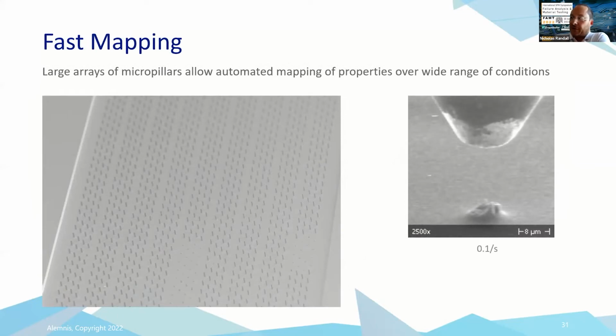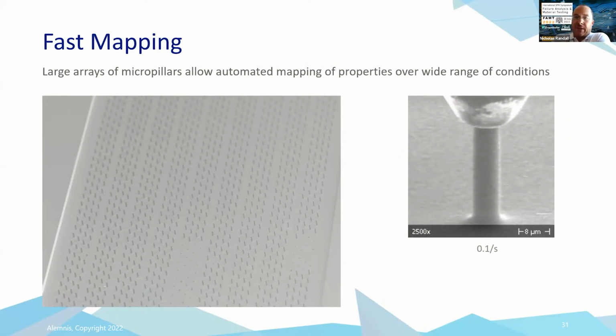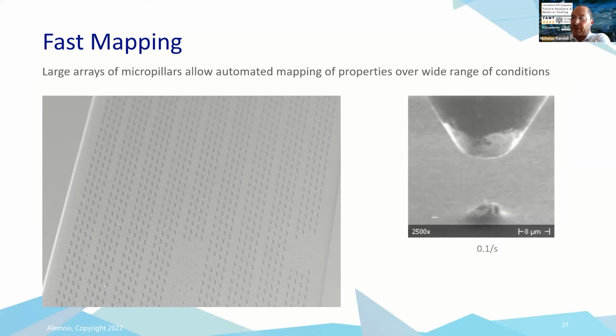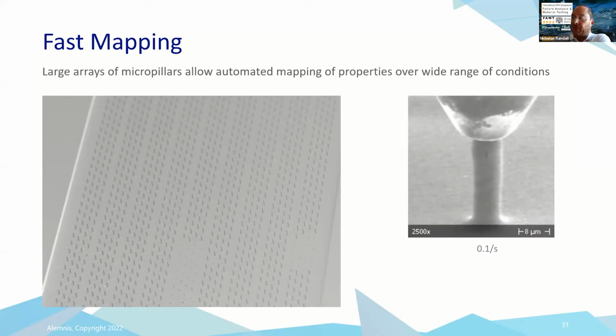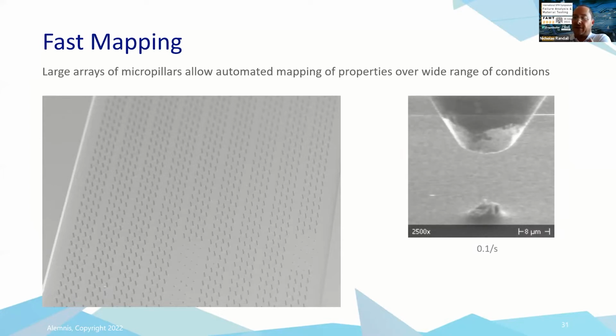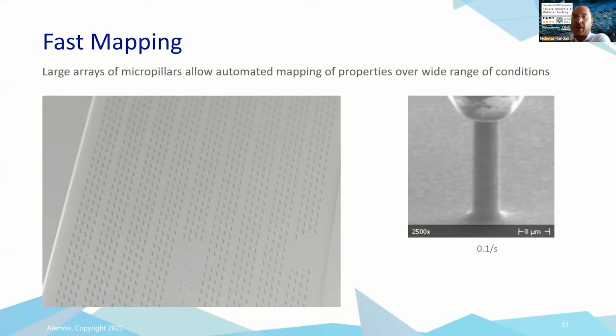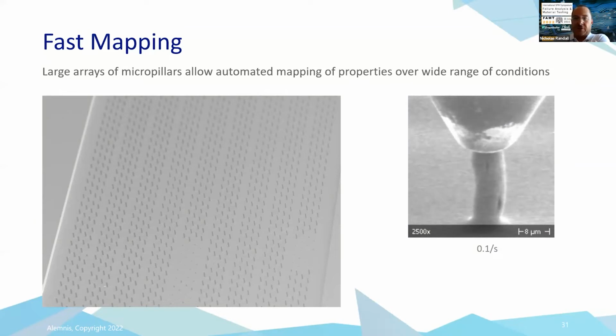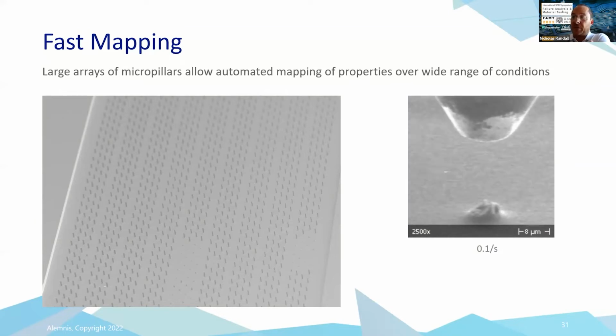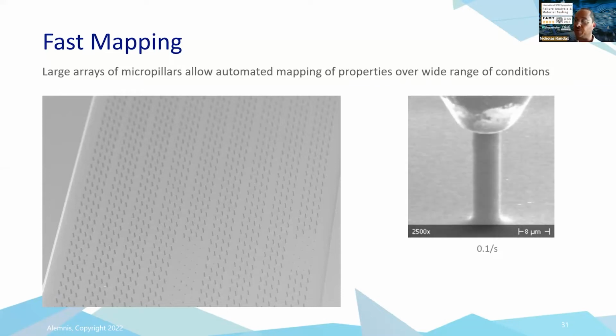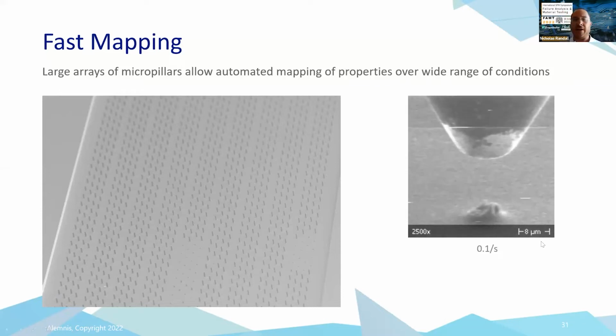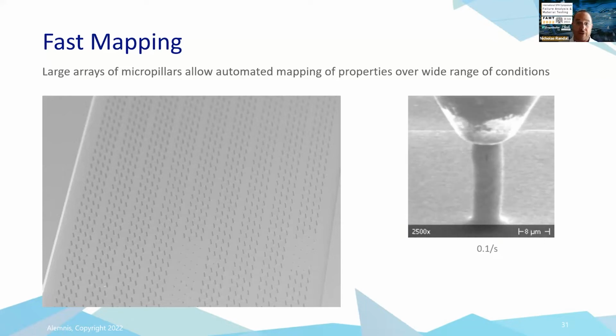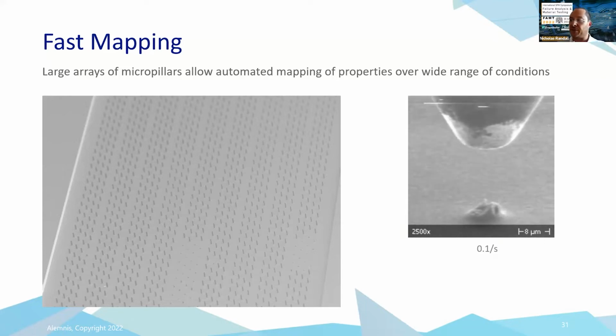One thing that's useful is combining the mapping advantage with arrays of pillars. So we're able to make arrays of pillars, especially in semiconductor materials, using lithography. If we did them by focused ion beam, it would take days and days. But we can make an entire wafer of pillars in the space of some hours using lithography. So this means we can program the machine to test every pillar with different parameters, and very quickly and in an automated way, get a lot of data to put into our models.